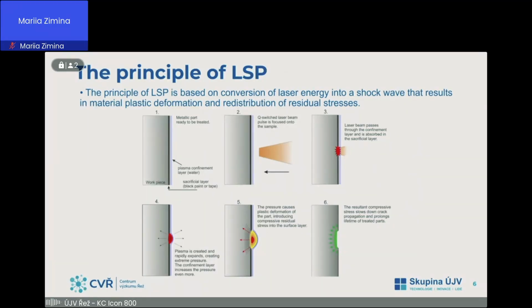Okay, and a few words about the principle of LSP. The principle of LSP is based on the conversion of laser energy into a shock wave that results in material plastic deformation and a redistribution of the residual stress. There are 3 steps of the process. In the first step, the metallic surface is covered with a sacrificial layer, obviously like black paint or tape, or without tape when we use the method under water, and a plasma confinement layer, obviously water or it can be glass. Then the laser beam pulse is focused onto the sample, and the laser beam passes through the confinement layer and is absorbed in the sacrificial layer. Only in the sacrificial layer, it's important, not in the surface of the metallic treatment.